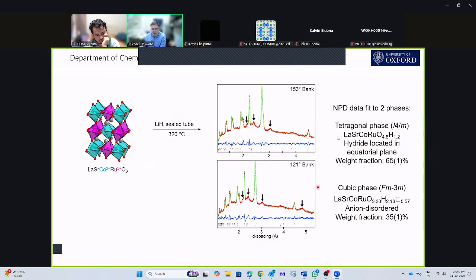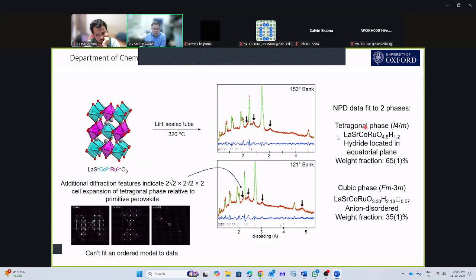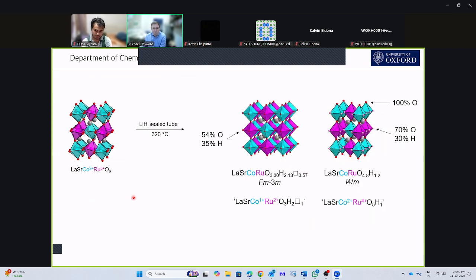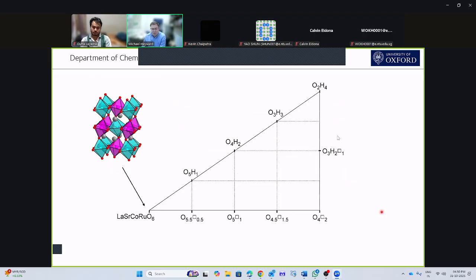And if we look closely at the diffraction pattern, we end up with a series of extra peaks associated with this tetragonal phase, which we can see arise from oxide, hydride, and vacancy ordering. Unfortunately, we can't solve the additional structure for this, showing that it's partially ordered in the anion lattice. But what we see is the product of the reaction is something that looks a lot like LaSrCoRuO3H2 and LaSrCoRuO5H1. So we've got quite a large number of different phases here, so it's helpful to organize them on a